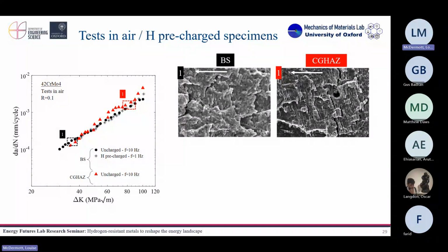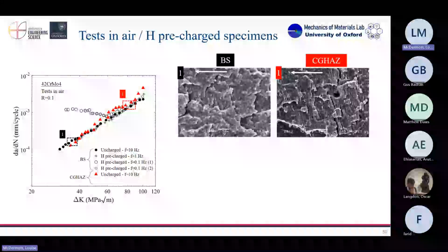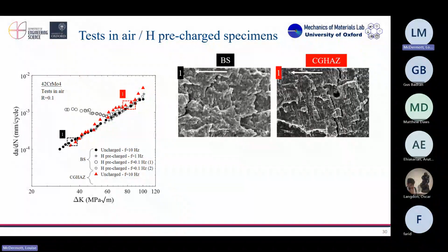So we did the same then for hydrogen. We can see that we have a completely different behavior here. So what happens is that crack growth rates have increased a lot, basically at the beginning of the test, and they tend to overlap the rest of the curve, so the, let's say, non-hydrogen part of the curve for higher values of delta K.